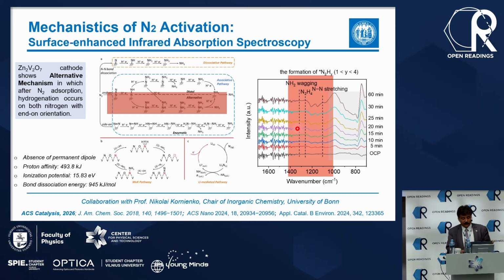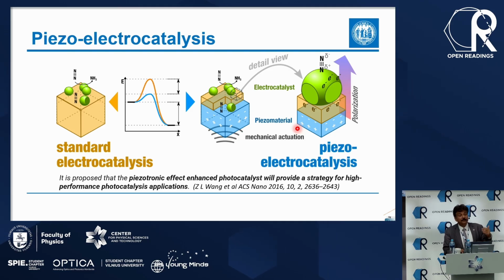I said we have to look into new processing, and there is a new area coming up. It's called piezocatalysis. Piezo-catalysis is just taking a piezo material, and I think you know what piezo material is. It's basically you apply mechanical force, you displace charges, and you create a piezo potential. Now, if you can do that, your surface is polarized. And on a polarized surface, you can even polarize a molecule like nitrogen, because you just need a slight fluctuation of the electron density, and that's enough for a chemical attack. This is how the entire chemistry is working. When you look at the collision theory, if the electronic cloud is a little bit delocalized or displaced, you create transient dipoles. And this is when the molecules get activated.